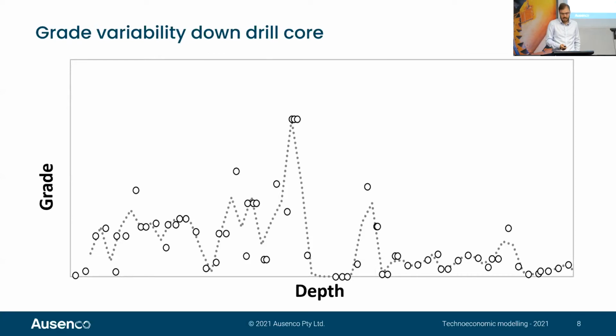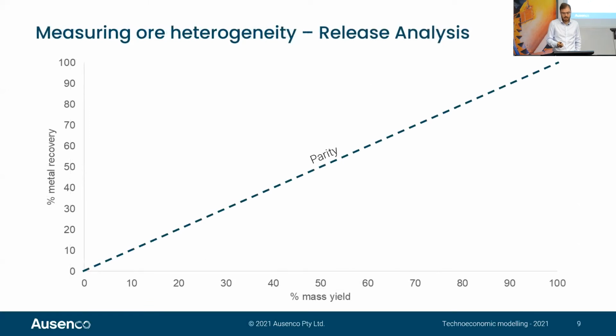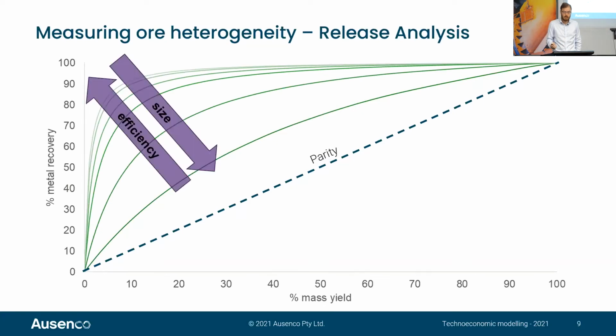There's another data set. But what we do with that is we plot it on this release analysis, which has been done for a long time, where it has mass yield versus metal recovery. The parity there would be if all the mass and the metal went in line with each other. And the further away you get from that 45-degree line, the more separation occurs between the metal and the mass. And so the efficiency improves and also the size increases as you get further from the parity.